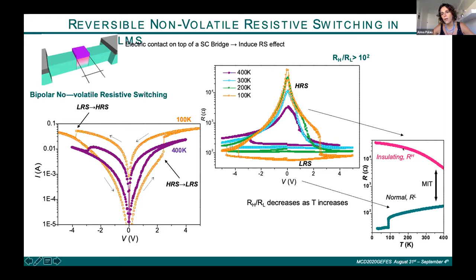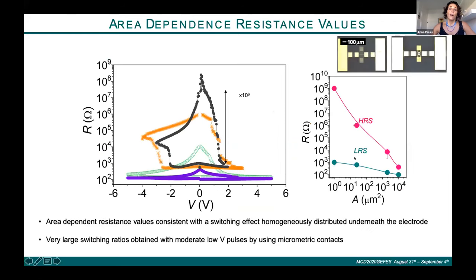And this is according to the temperature dependence of the resistance in the insulating and the metallic superconducting phase, that here we have an increase of the resistance and here we have a decrease of the resistance, giving us higher ratios at low temperatures. We have also evaluated the dependence of the switching performance on the gate electrode area.